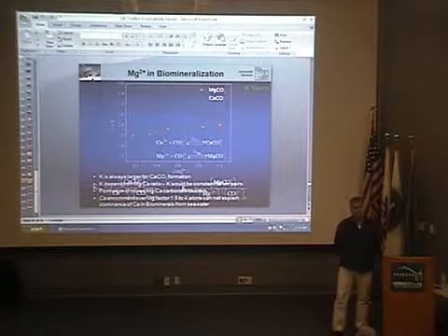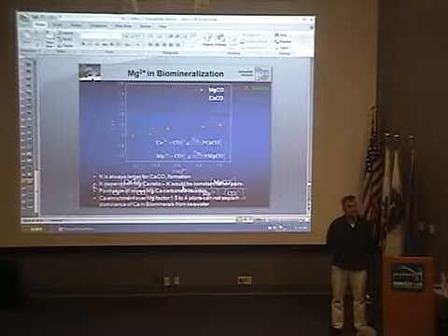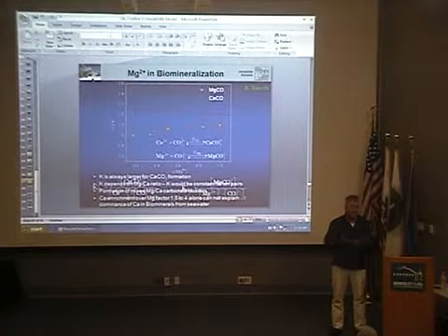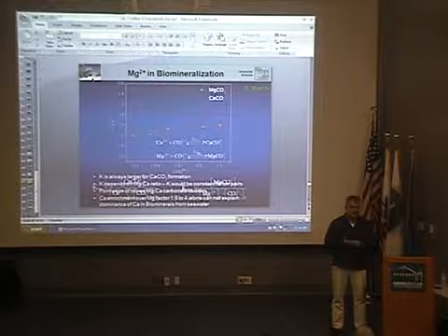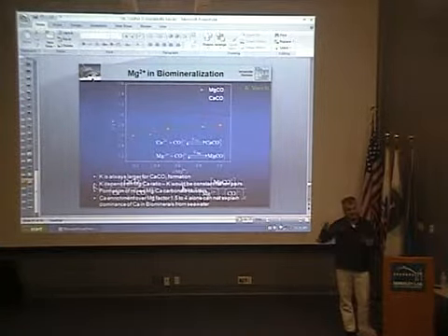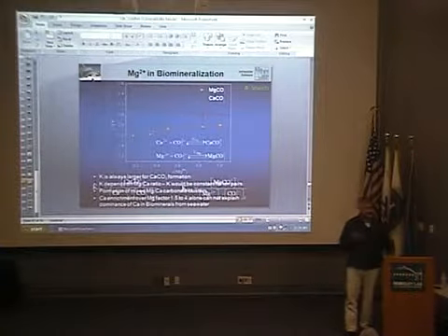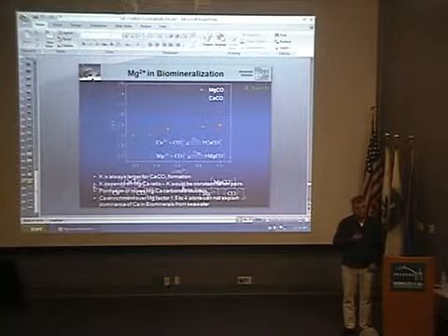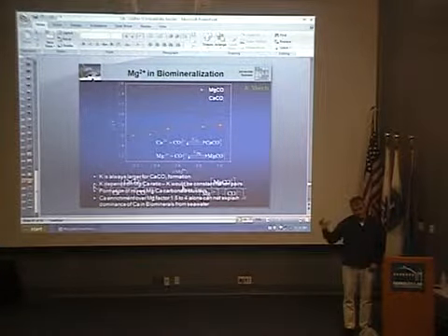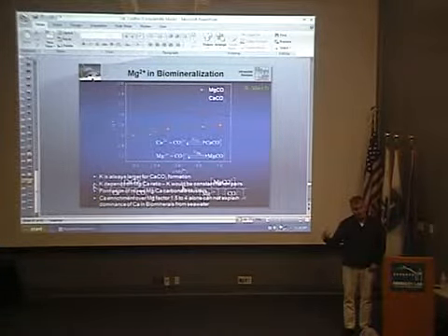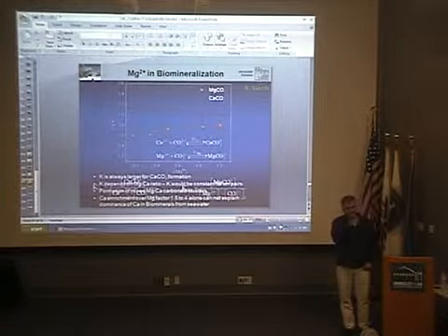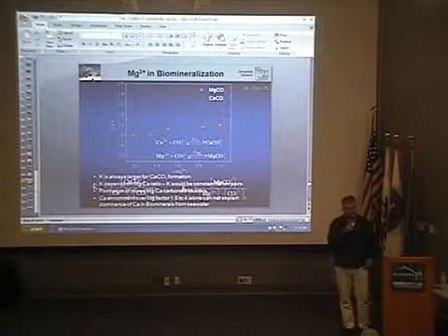The thing is, Dennis was doing equilibrium thermodynamic calculations on the clusters, and you can describe them by equilibrium thermodynamics. So you applied mechanisms known from protein aggregation to describe protein aggregates, essentially, and they also describe cluster formations. But to point out, they are not stable towards the amorphous calcium carbonate, which is formed later, because otherwise it wouldn't form, but they are stable towards the ions, which are there initially. So this must be distinguished.